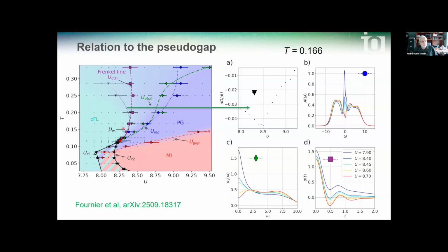I will come back later to the Widom line that indicates extrema of thermodynamic quantities. The line labeled U_inc, for incoherent, corresponds to loss of the quasi-particle peak in the single-particle spectral weight. The line labeled U_σ(ω) corresponds to the loss of the Drude peak. You can see the famous mid-infrared peak. The line U_σ(T) is what we call the Frenkel line. Notice that contrary to the Widom line that ends pretty quickly at high temperature, the Frenkel line continues to high temperature.